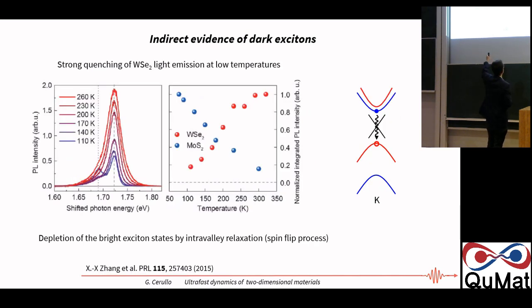And indeed, if you look at how the photoluminescence goes with temperature. Normally in a semiconductor, you expect that the lower the temperature, the more it emits. So in MoS2, that's what happens. If you decrease the temperature, the quantum yield increases. But in WSe2, which has this opposite spin ordering, if you decrease the temperature, the photoluminescence decreases. Why? Because you are trapping into this lower exciton and you don't have enough thermal energy to escape from this trap. So you end up in a state that doesn't emit.